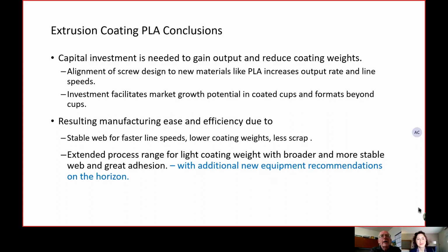And I think the other critical factor here is that the structure and design of this polymer in itself improves the stability of this web, which allows us to get to these higher line speeds and the lower coat weights. And the stability and reducing edge weave reduces the amount of scrap that's produced as well. So this all goes to getting a coated paper product that is more viable in the market because we're coating with a little lighter coat weight and higher processing efficiency with the stable web and good adhesion. So we're excited to be doing this work with some equipment modifications that will allow us to improve the processing as we go forward with these new polymers.